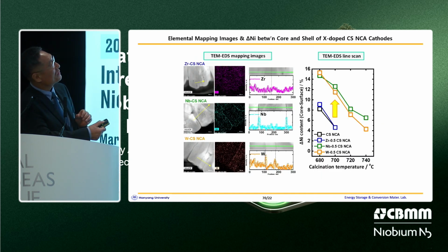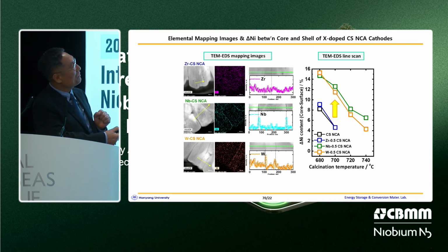And this is the TEM-EDX mapping and the line scan image. As you can see here, the zirconium ion is homogeneously distributed throughout the particle, whereas niobium and tungsten ions are segregated at the grain boundaries, and especially the niobium ions.